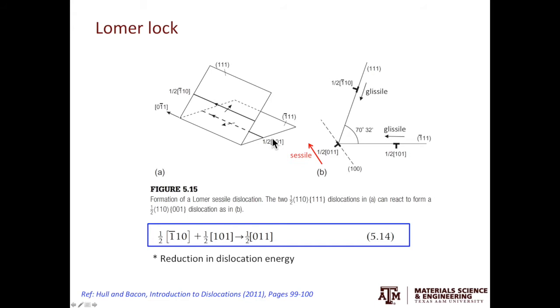For the second dislocation, it glides on 1-bar-1-1 plane and with the half 1-0-1 Burgers vector. The figure on the right shows the side view of the figure on the left. Now, we have those dislocations gliding on these two slip planes, and they meet at the intersection.